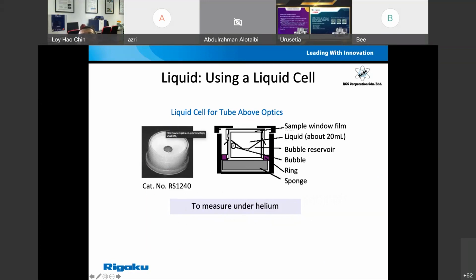So this is a liquid cell. Okay, and this liquid cell is specially built for a tube-above system, because normally if you pour liquids into a cup, the top surface might be covered by air bubbles, or there might be some air bubbles inside the cup. So in this cup design, we can ensure that all the air bubbles are trapped underneath these funnels. So the measurement surface is always clear of bubbles, to ensure that you can have a very nice measurement result without the effects of air bubbles. Okay.